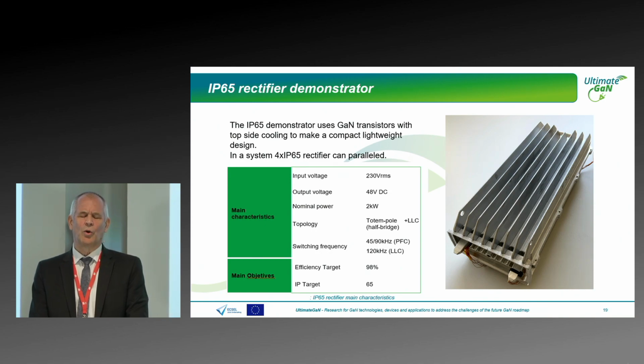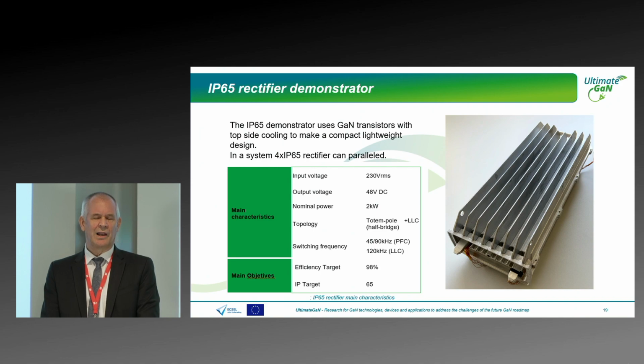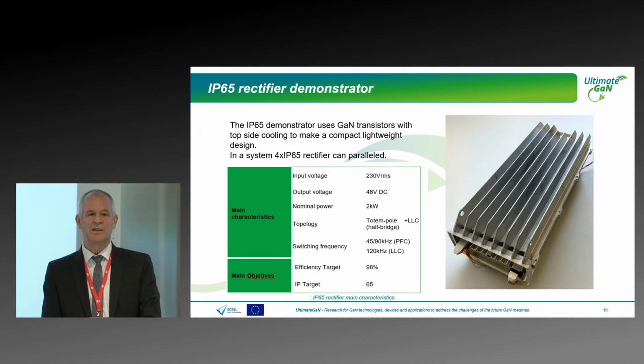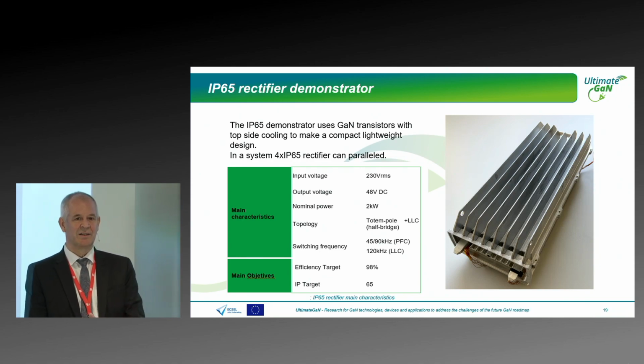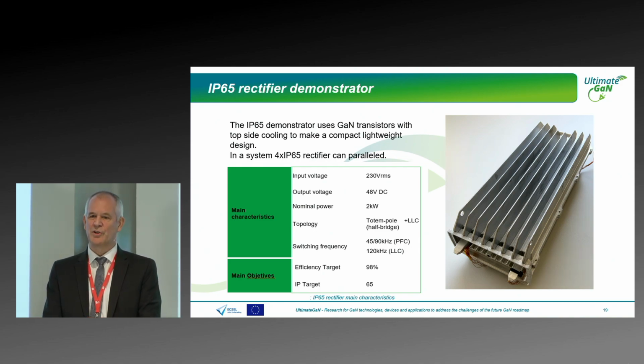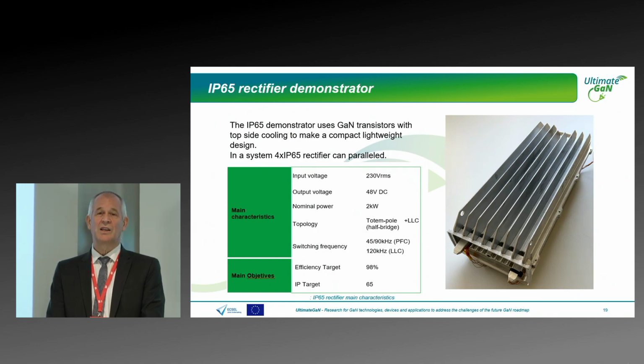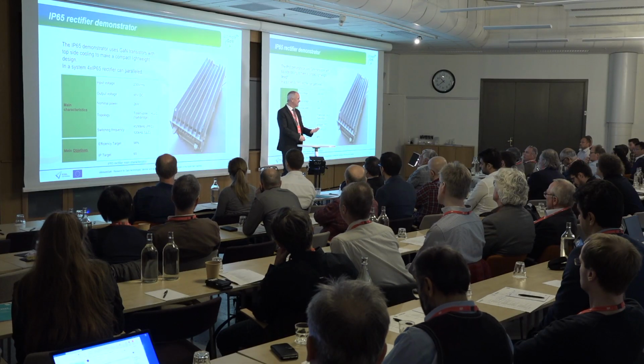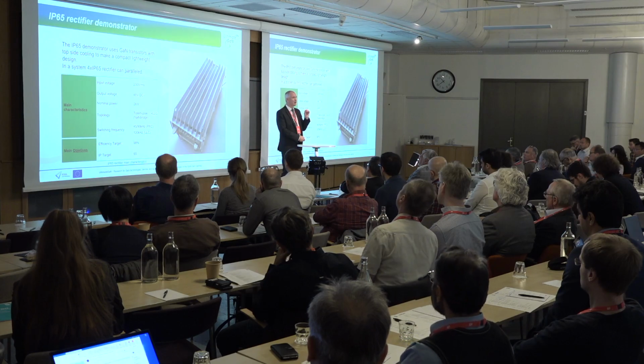And here, this is also, for me, a very good signal. In the last project, they did a server power supply with 97%, which was 2% over the market. So really, 4 years ago, it was the most efficient server power supply. And they used it in the field. So you have it in the field with 150,000 power supplies they used, with even more gallium nitride switches. And we had 3 returns, but these returns were not caused by the technology. This was topside cooling, and the joint of the device to the cooler was bad. It was overheating, but 150,000 and no technology related field return in an IP65 application.